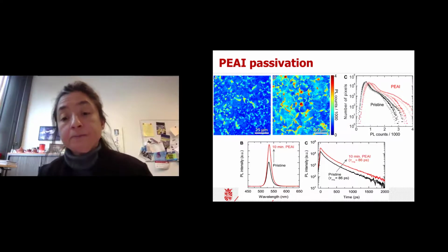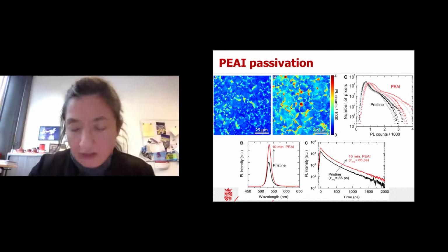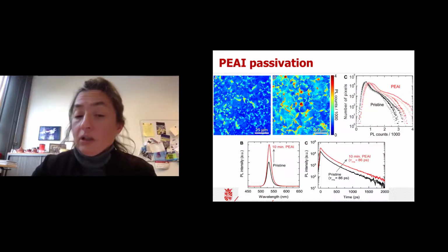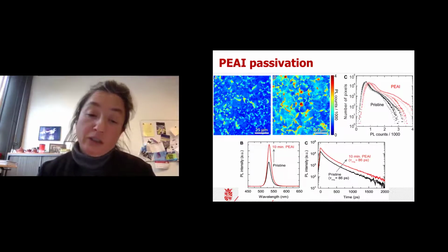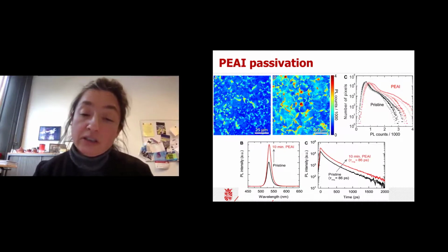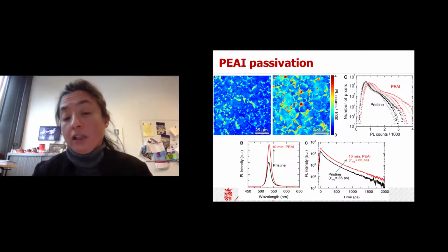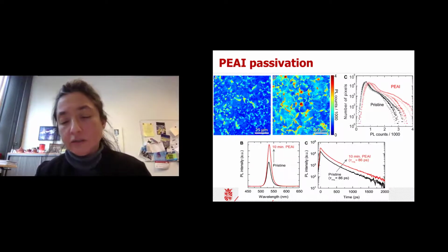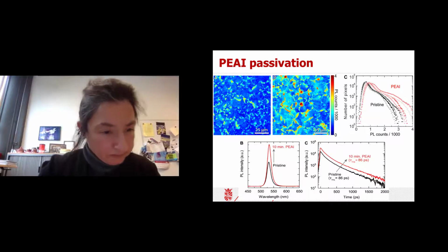As a last piece of evidence, the lifetime is actually not changed, but because the photoluminescence intensity is increased, it is indeed a time zero phenomenon. So it's something like an increase of the population of the excitations at very short time.